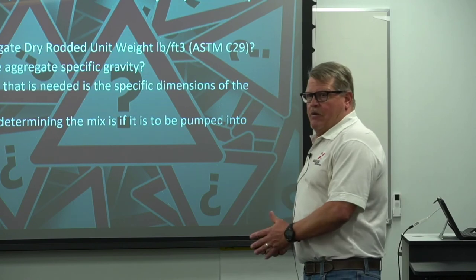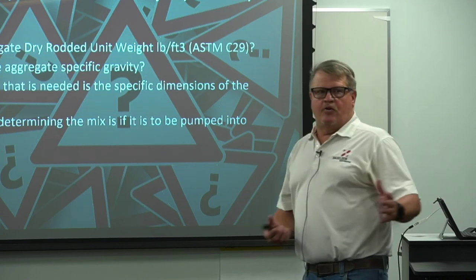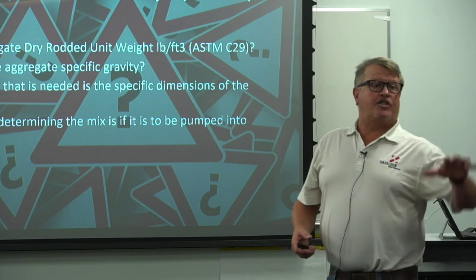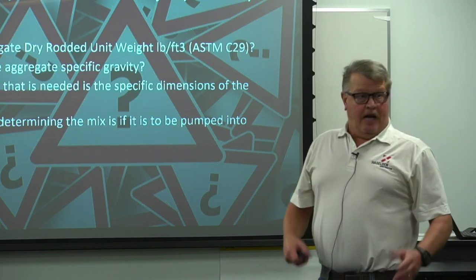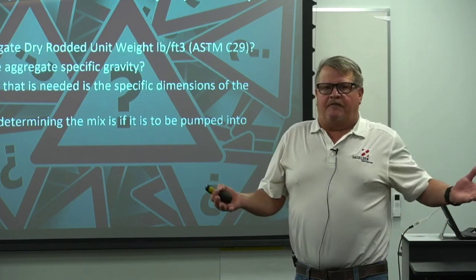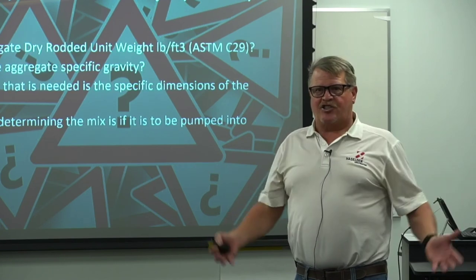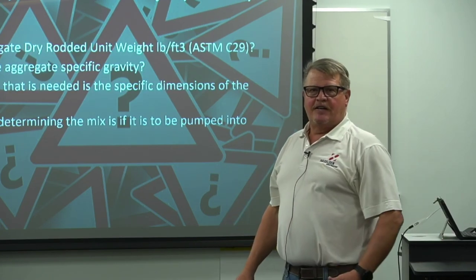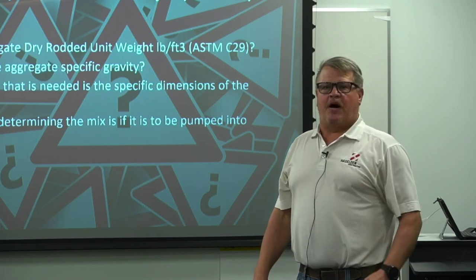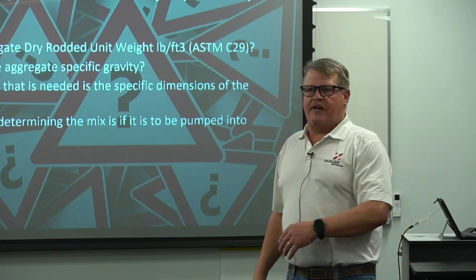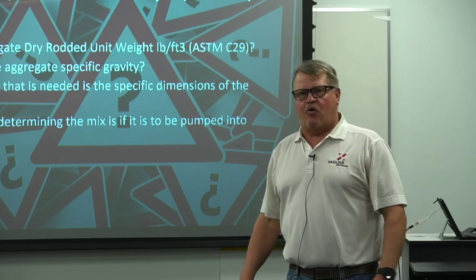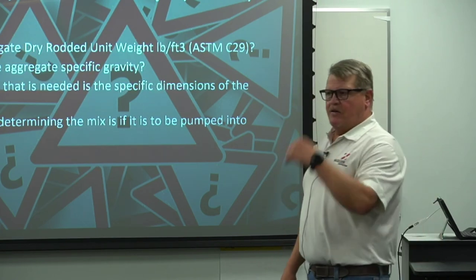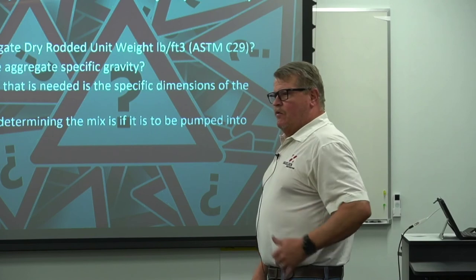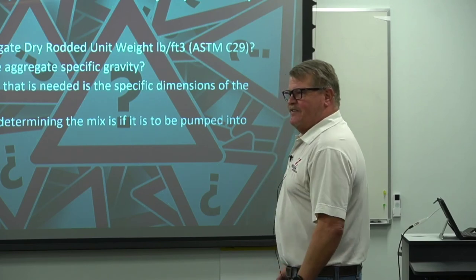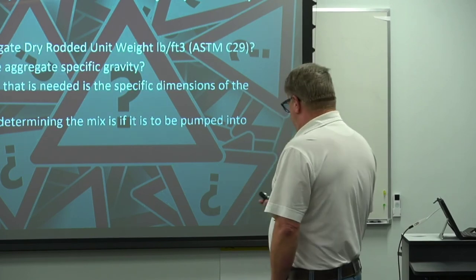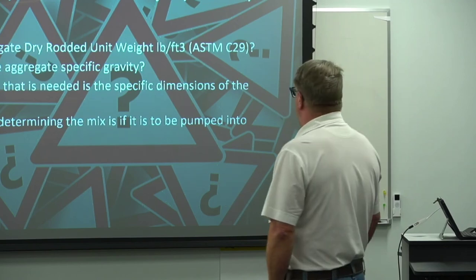So I used to use the slurry packs, right? Then we'd get grout and we dilute it and send it through, and architects and engineers started seeing problems in their floors and the clients, because you're basically putting a 1500 PSI on the slab with a 4,000 or 5,000 pound mix. And your finishers will leave you a wet spot because the whole floor, 10,000 square feet, set up, and that 600 square feet in the corner is wet. And they'll walk. And then somebody's going, we need to grind this down before the floor guys come in, huh? So it's just things to keep in mind. And whether it's rubber and steel as well.